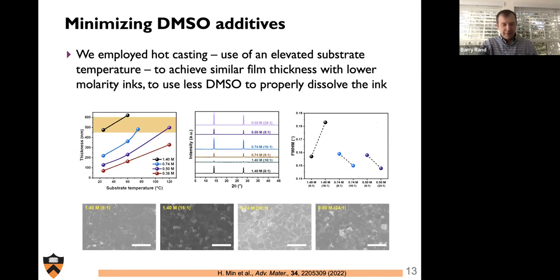Yeah. So the way that these were made, it's first the full architecture. It's an FTO substrate, so sputtered FTO on glass, and we deposit tin oxide by chemical bath deposition, and then it's a formamidinium MA based ink, which is deposited with, in this case, a hot casting procedure to try to minimize DMSO as much as possible. And then it's followed by the doped spiro-OMeTAD and gold.